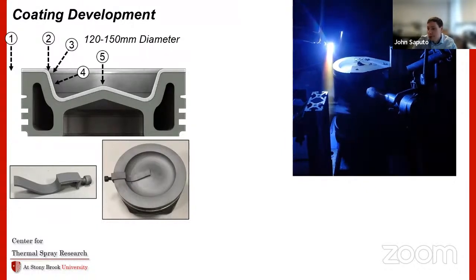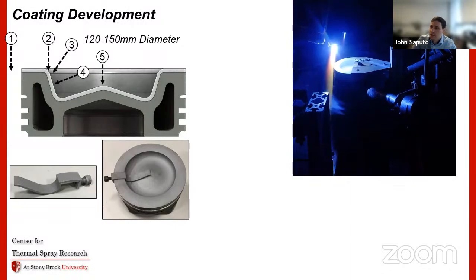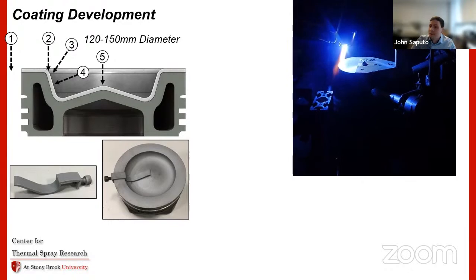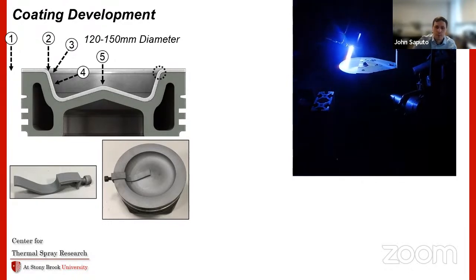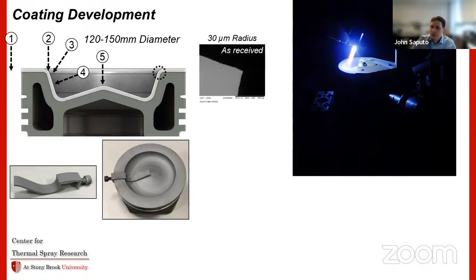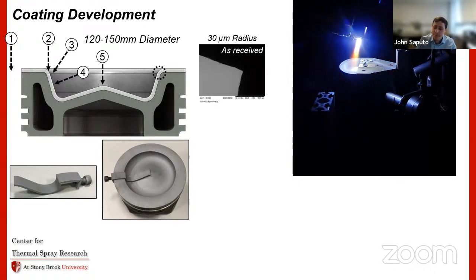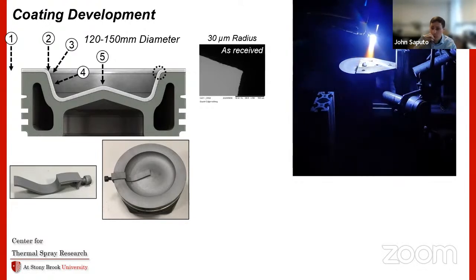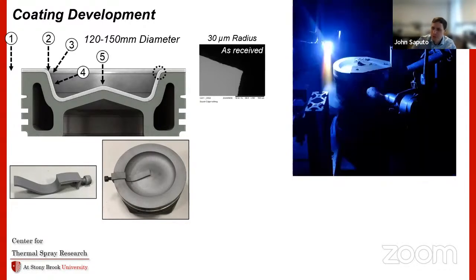So when you're spraying these coatings, it looks something like this. We're generally rotating these parts and traversing the torch along the center line, keeping it normal the entire time. So if I look at one single feature on here, it says bowl edge is what this part of the piston is. It generally has a specified dimension as fine as about 30 microns, which is kind of difficult to do with some spray processes.